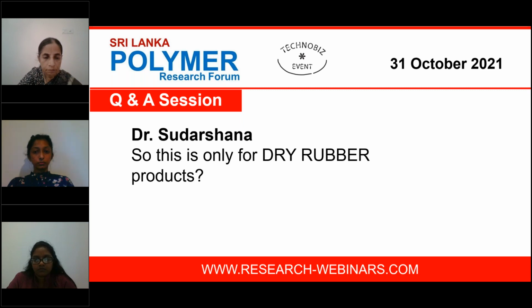So if we use this for latex, we actually need to check what happens to the properties of the latex product because of the surfactant. Normally I recommend this because once we add the clay into the rubber, I separate the clay layers as much as possible, so the clay layers are better dispersed.